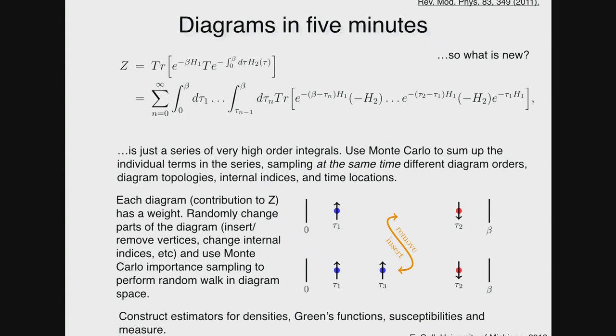By sampling different topologies, different internal indices, and different time locations, you can then recover the value of that partition function or measure observable with the weight that they contribute to this partition function. Each diagram, or each term that I showed in this expansion here, has a weight. We randomly take a diagram, so we change it by inserting or removing vertices, by shuffling around lines, by rearranging internal indices, and so on. And we can use a Monte Carlo importance sampling procedure to walk through diagram space, and in this way, randomly sample all of these terms in that series above.